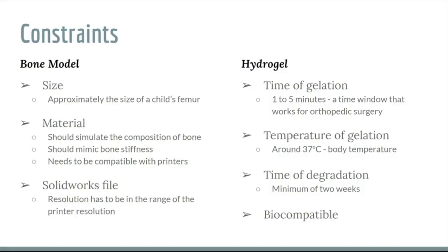For the hydrogel, constraints were time and temperature. It needed to gel within 1 to 5 minutes because that's the range for surgery, and at around body temperature. And the time of degradation needed to be a minimum of 2 weeks. And finally, it needed to be biocompatible as it was going inside our body.